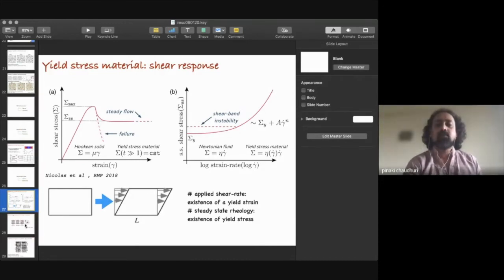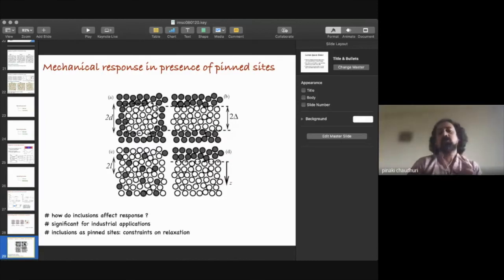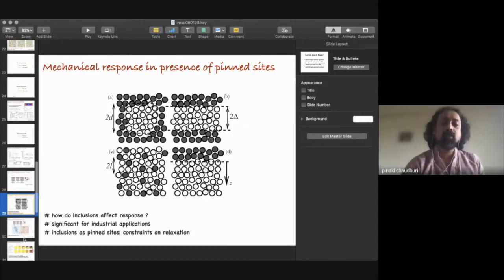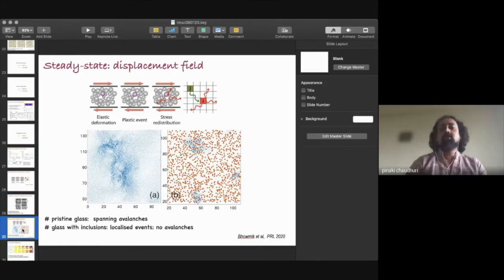Okay. So what we looked at is, if I have a glass forming system where I apply some pinned sites and essentially inclusions into this glassy material, then how does the system respond? So these are like inclusions or impurities that you impose inside a glass forming mixture, and you then apply the mechanical shear. And what one observes is the following. This is the standard schematic picture that one has in mind: if I'm applying this shear, initially there is some elastic deformation, and then beyond a certain threshold, some plastic event happens.